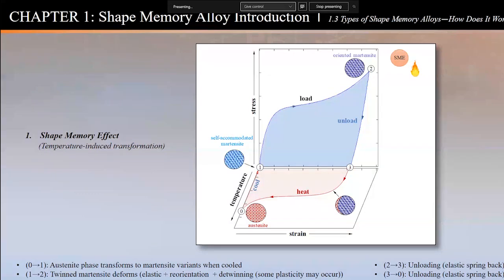Now I'm going to take my piece of metal and I'm going to deform it. I'm going to go from 1 to 2. If I didn't tell you anything about this material and I unload to 3, it could look like an elastic plastic deformation, like you pull on a piece of steel. If I don't show you the bottom half here, just the blue curve, load to 2 and load to 3, remove load. So this deformation, in the order of 6 or 7% in some alloys, is isothermal. It's done at a constant temperature, say, for simplicity, room temperature.